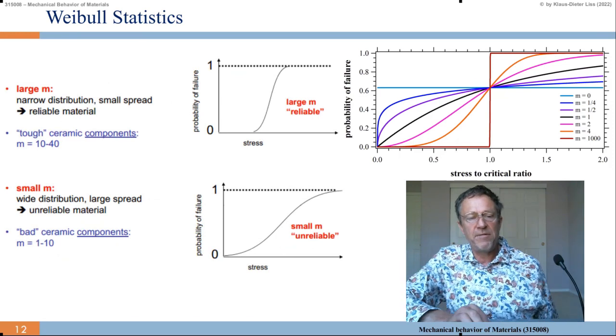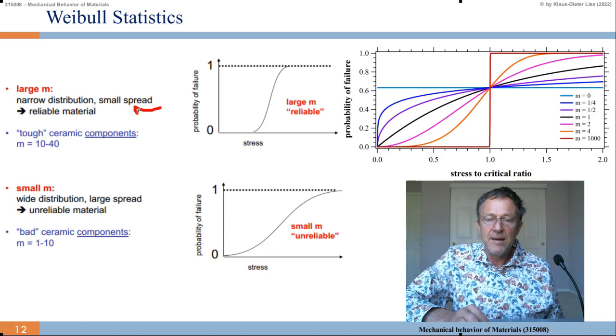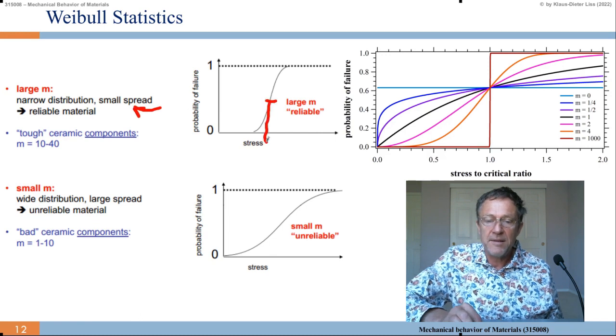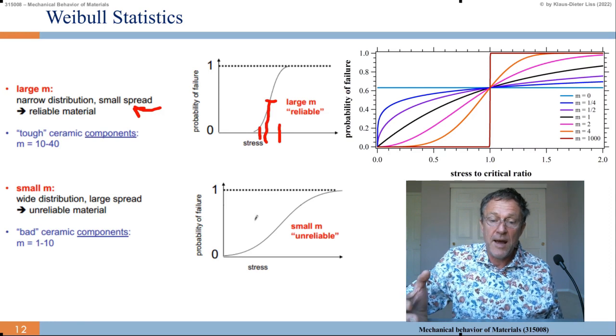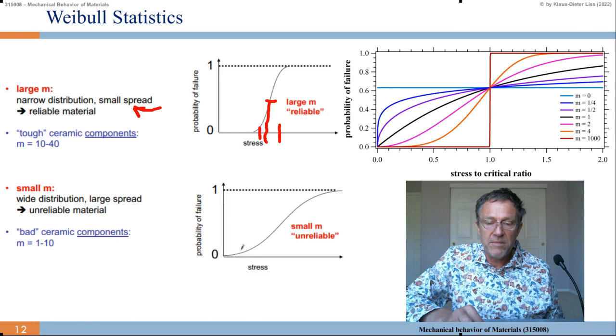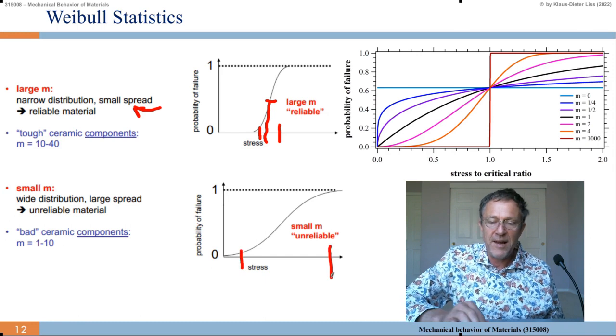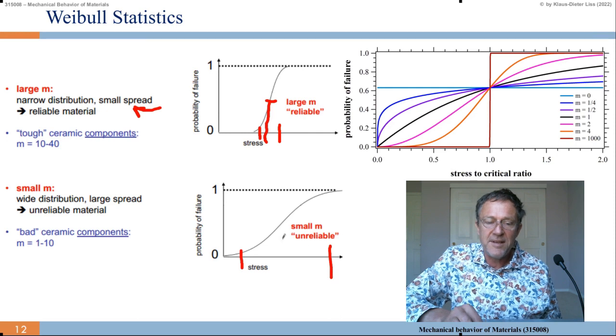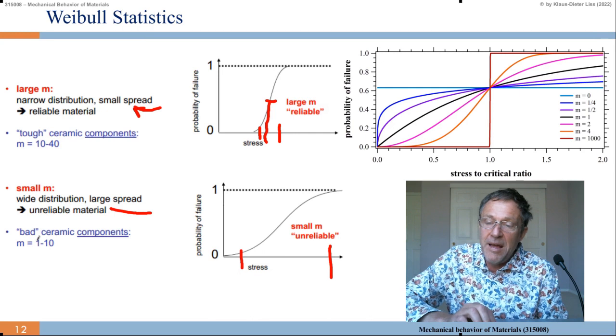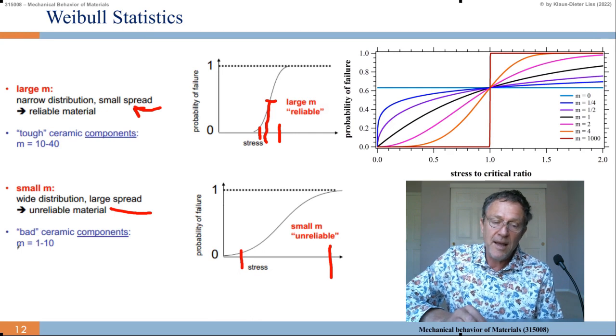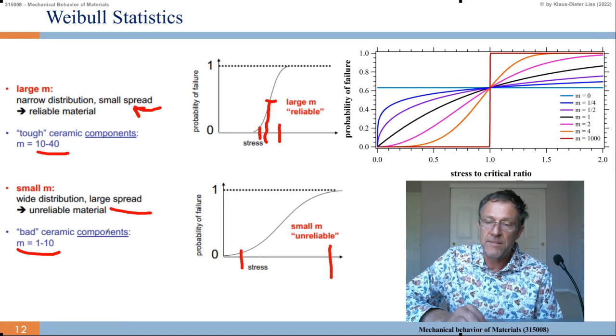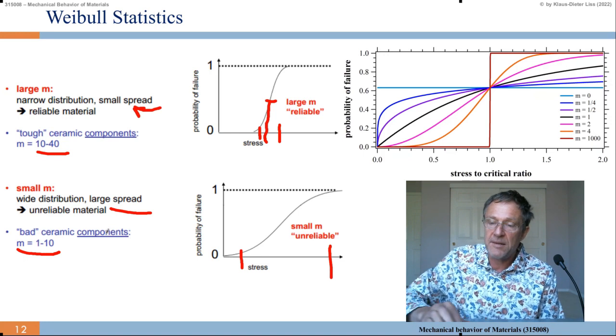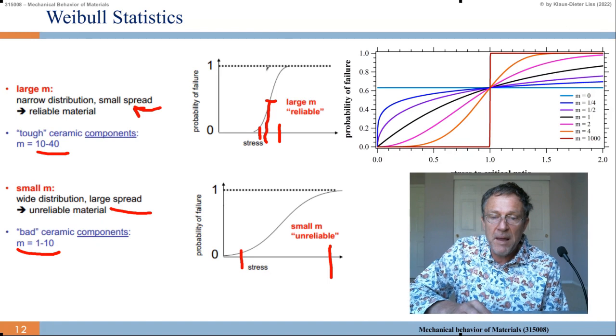So for large m, we have the narrow distribution and a small spread. That means the material is reliable. It falls somewhere in this range. It's reliable. For small m, we have a wide distribution, so it can fail here, but also only fail at way higher stresses. So this is hard to predict. It's an unreliable material. So for bad ceramic components, bad in a way looking at fracture, the m is 1 to 10. And for tough ceramic components, it's 10 to 40. And for metals, it goes to 100. 100 I haven't shown here, but it is maybe something like that.